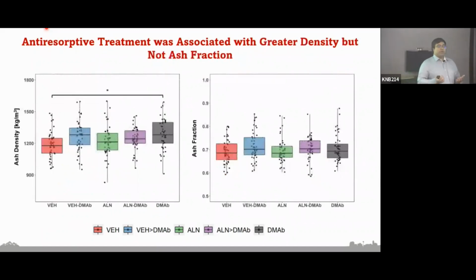Our density measurements were also pretty much consistent with things in that we were able to detect increased density in the antiresorptive treated groups, particularly the denosumab alone group. And I think it's really cool that we didn't see a difference in ash fraction, because I think that would seem to indicate that what these drugs do is they don't necessarily change the composition of the tissue, not the ratio of organics to mineral, but really their effect on density, I think it seems, is more based on what they do to the pore space of these bones.